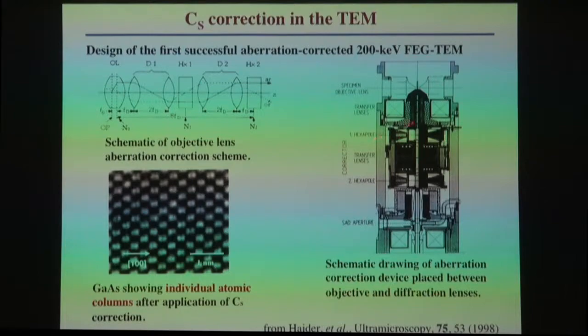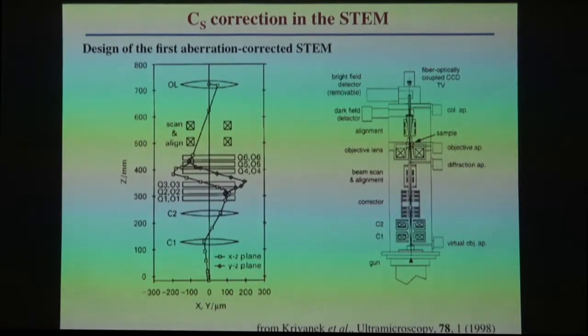So there are two transfer lenses just here, a hexapole, two transfer lenses, and a hexapole. You just add to the length of the column, and you're able to get the aberration-corrected device inside the microscope quite easily. And this shows where Haider and colleagues were able to resolve the gallium and arsenic dumbbells once they applied CS correction to that particular microscope.